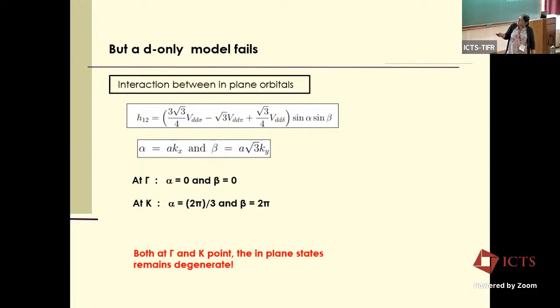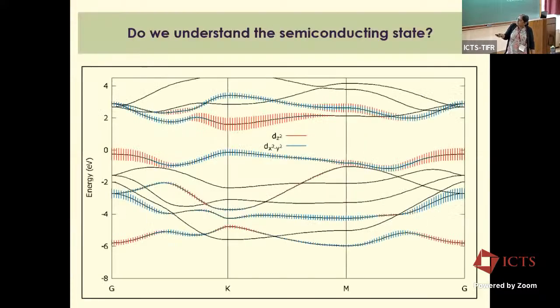So what does that imply? Going back to this figure, over here it's fine. It's the same as the crystal field picture that I presented. But over here you would have both the dx squared minus y squared and the dxy degenerate, which wouldn't explain why the system is insulating, because those states can hold only 2 electrons. Okay, and so this picture.